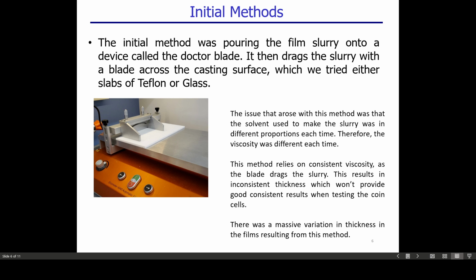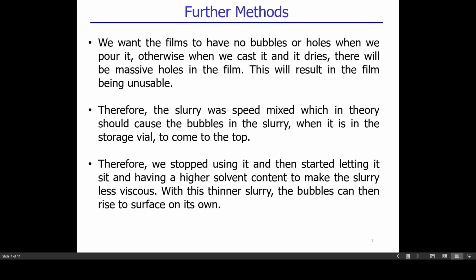And the issue that arose with this is that it relies a lot on consistent viscosity. However, since the solvent was used initially in the first few experiments that we did, the solvent proportion varied heavily, therefore the viscosity was different each time. So that resulted in inconsistent thickness from batch to batch and from one end of the film to the other end of the film. Therefore, there was a massive variation in thickness resulting from this method, which would not result in good consistent results in a coin cell.